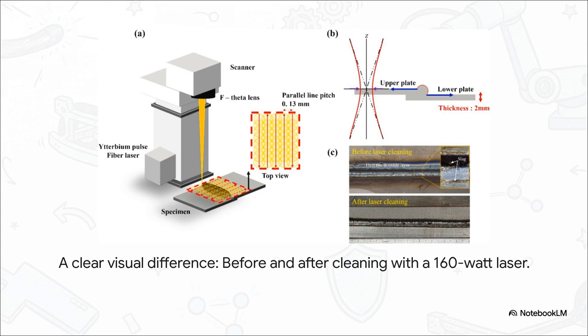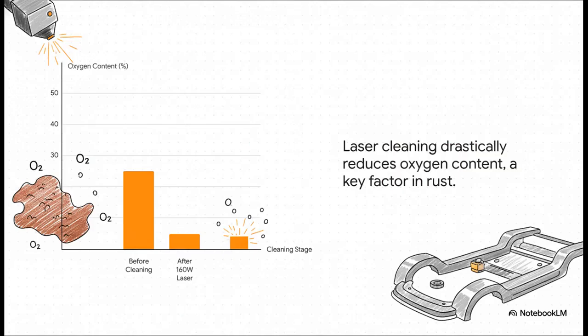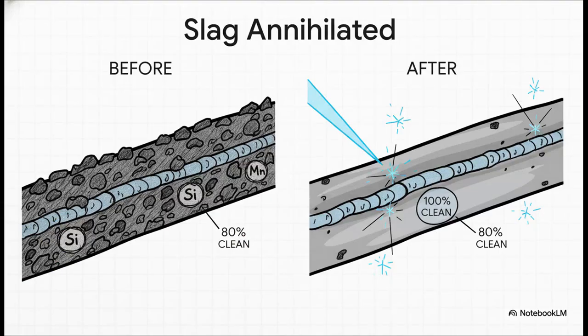The researchers actually tested a range of power levels and found that 160 watts was the absolute sweet spot for a perfect clean. We can actually measure the clean by looking at the oxygen content. Remember that oxide layer is what kicks off the rusting process. Before cleaning, the surface was over 25% oxygen. After the laser treatment, that plummeted to under 5%. That is a huge drop, and it's a crystal clear sign that the potential for rust has been knocked way, way down.